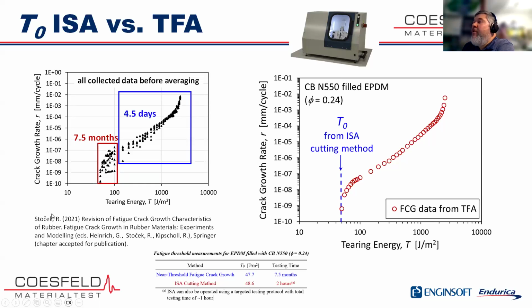And there's a paper I'm citing here, where we actually went back and ran both methods on the same material, and we were able to show that we ended up with measurements that were quite similar. So using the direct method, we measured, in this case, 47.7 joule per meter squared. Using the cutting method, we got a value of about 48.6.